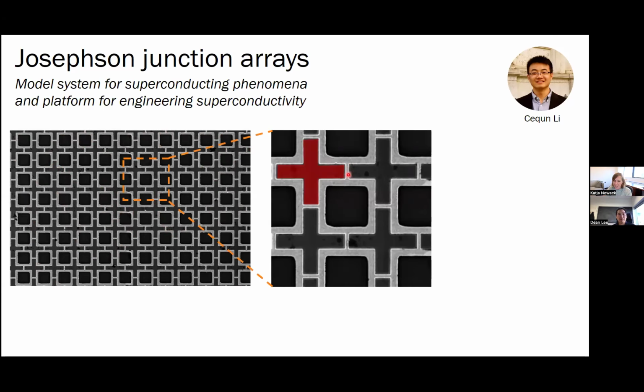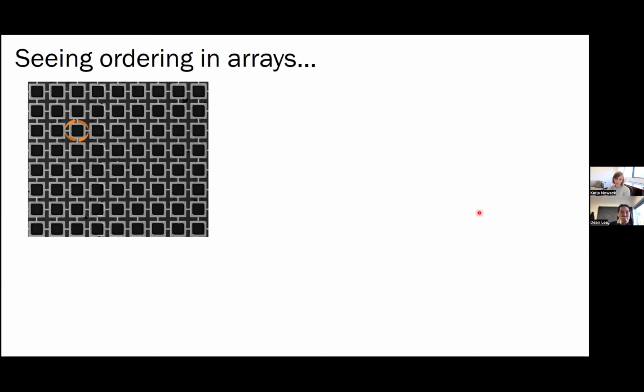And there are little gaps in between the crosses. At the gaps, you have superconductor, then gold, and then superconductor, and it turns out that also makes a Josephson junction. So we have a periodic array of Josephson junctions arranged in this square lattice. If you trap a vortex in this kind of artificial superconducting structure, there's a circulating current that goes around this little plaquette that you made. It will cross 4 of the Josephson junctions and have a current going around. This is a zoom in of the Josephson junction. If we just have this array and trap a single vortex, this is how it might look. In the magnetic image that we take of an individual vortex, the vortex is dark in color, and gives us this blob right at this plaquette.